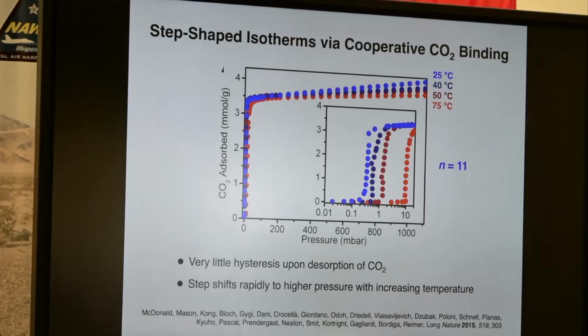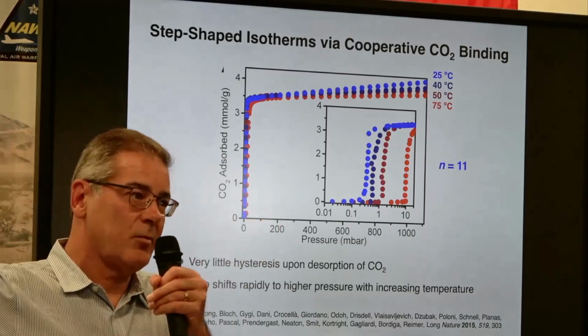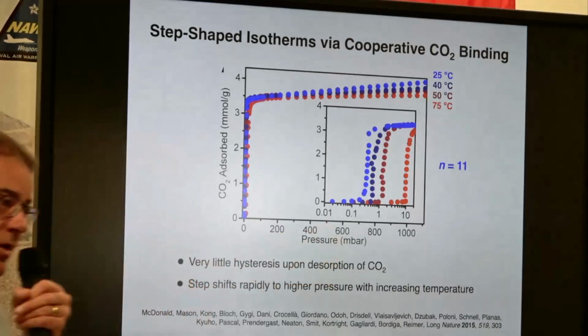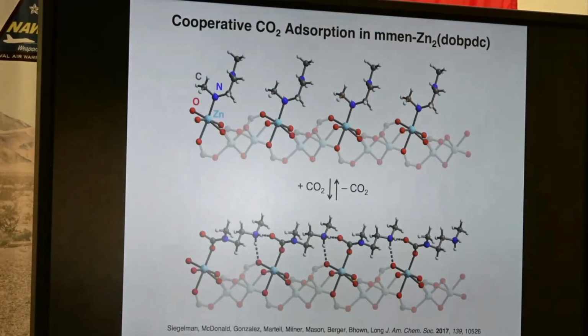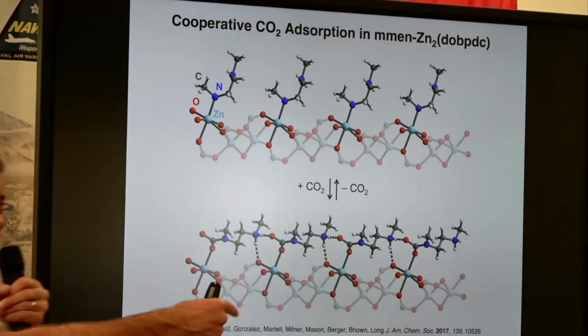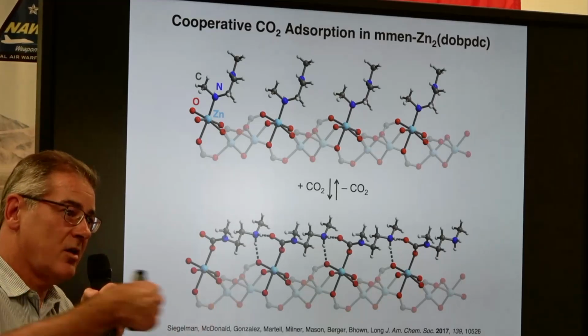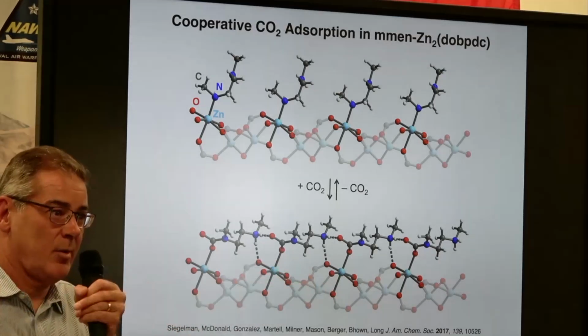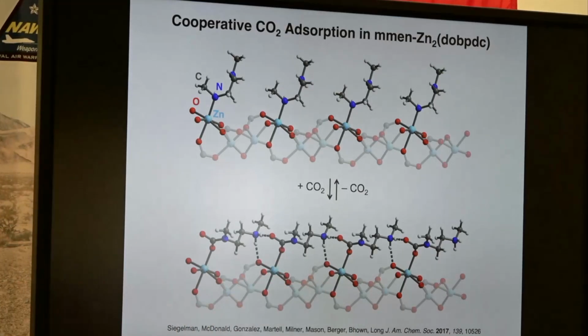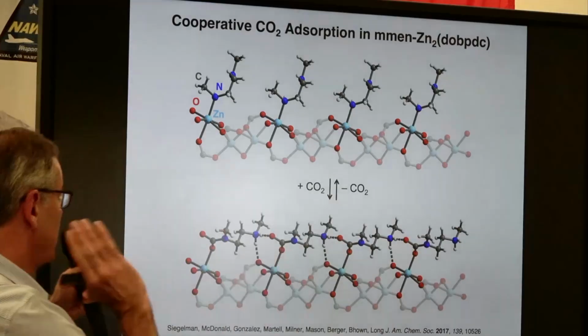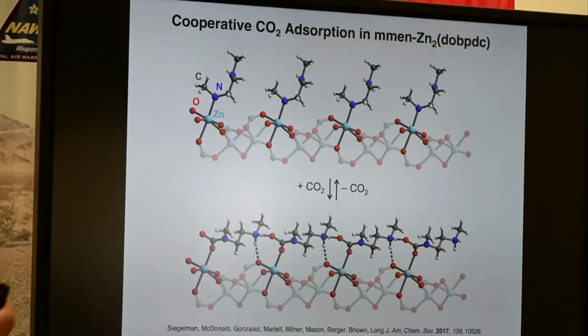That means on average it takes 11 CO2 molecules all together reacting to drive the reaction forward and make a product. And the product that you're making is a one-dimensional chain of ammonium carbamate that's running along the rows of magnesium with diamines bound along the channels. And so here you're seeing a slice. This is from crystal structures. You're seeing a slice along the side view along the row of metal centers. So this is zinc instead of magnesium for growing large crystals. But each zinc has a diamine. The top structure is before CO2 adsorption. Bottom structure is after CO2 adsorption.